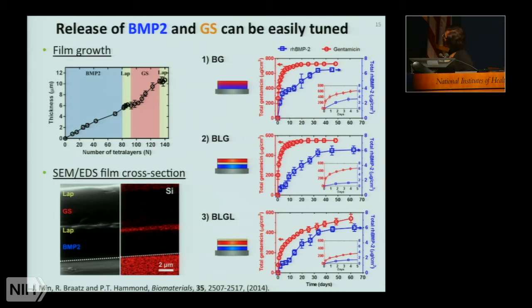We see a rapid release of gentamicin, and we do want enough to eliminate an existing infection, and therefore this bolus release is not bad. And we see that there is a delayed release of BMP2. However, we see that there's a significant amount of BMP2 that's coming out in the first 4 days, where this x-axis is in days, and here we're seeing a blow-up of that release behavior.